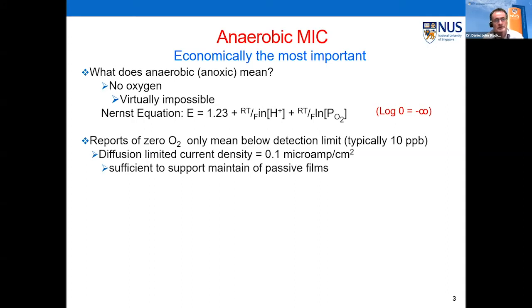So when you read reports of 0 oxygen, people often say they've measured 0 oxygen. What they actually mean is it's below the detection limit of their equipment, which is typically, most oxygen detectors tend to be based on a current, right? So they're typically somewhere around 10 ppb. And if you work that out, using Fick's first law of diffusion, you'll find that 10 ppb oxygen can support about 0.1 microamps per square centimeter. And that's actually plenty to maintain the passive film on stainless steels and titanium. So if you put titanium or some stainless steels in a 10 ppb environment, its open circuit potential will be positive of the reversible hydrogen electrode. So actually there's still enough oxygen in there that essentially there's oxygen at that surface maintaining the electrochemistry.